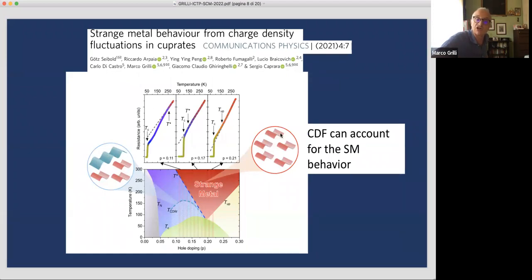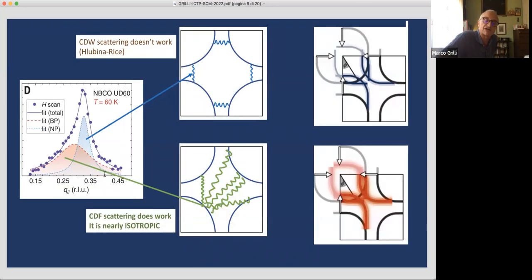Okay, and the question then arises naturally. Could it be that these charge density fluctuations, which are so short ranged and therefore mediate an anisotropic scattering, are responsible for the strange metal behavior in the cuprates? And the answer is actually yes. So if you take the charge response function, you see that the charge density wave narrow peak suffers this Hlubina-Rice argument. So when you fold the Fermi surface by QC in order to identify the hot and cold regions, you find that indeed there is a sharp separation between the hot and cold regions, whereas the excitations due to charge density fluctuations are broad.